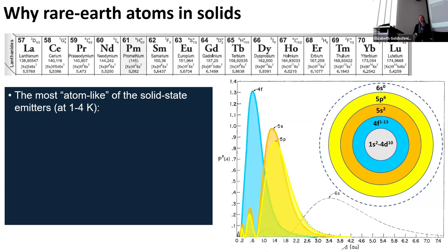When you go into a solid, you break symmetry, especially if it's a highly non-symmetric site, which means that you get a little tiny bit of admixing. Your spherical harmonics are no longer perfect wave functions. So in fact, what you do get in practice are weakly electric dipole allowed transitions between spin-orbit split levels that are still mostly 4F in character. So you do have the problem that your light-atom coupling is extremely weak, which we're going to talk about in a second. But the shielding is really a huge benefit.